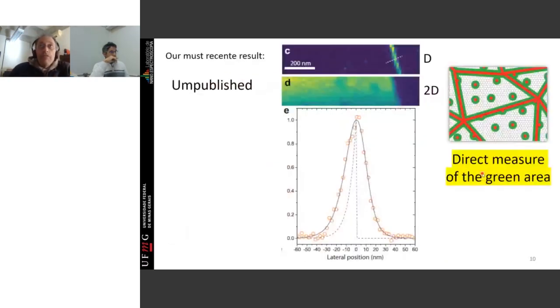And if I go even further, here is the image of graphene. The graphene ends here. And this is an image of this defect-induced peak. And you can see that the defect range or the grain, the end of graphene, you can image with a resolution on the order of nanometers, okay? It's like if you are here imaging exactly this green area because the graphene ended here, okay?